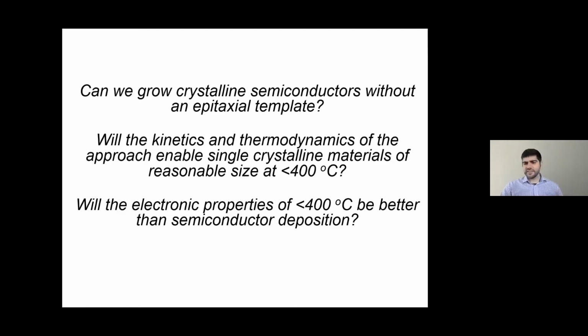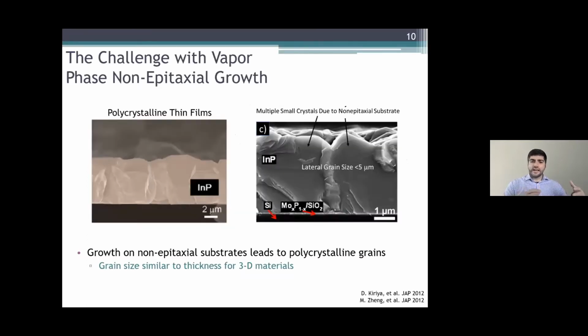Now, it turns out that the challenge behind growing on non-epitaxial substrates can really be encapsulated by these two SEM images. They're SEM images of indium phosphide grown on molybdenum metal, a non-epitaxial substrate. On the left-hand side, it's grown using close-space sublimation, and on the right-hand side, using MOCVD. With these vapor phase growth techniques, you run into a limitation where the lateral grain size tends to be on the same order of magnitude as the thickness of the material. You can actually see that in these images. This is a grain over here, this is a grain over here.